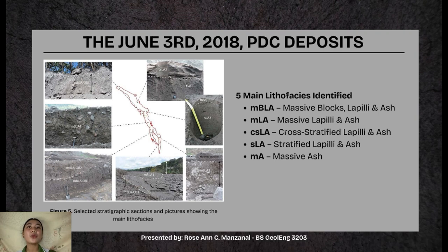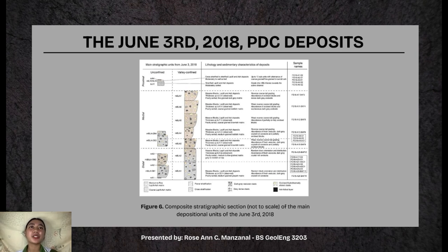In contrast, the overbank deposits form when flows spilled out of the main channels. Some created wedge-shaped layers near the valley walls, while others were redirected into smaller tributaries. These were typically less sorted but still carried large blocks. They also found ash cloud surge deposits, which were layered and sometimes showed small dune-shaped structures. These lighter, more distant deposits often left thin ash layers and scorched vegetation, helping trace the timing and extent of the surges. By analyzing these deposits and their structures, scientists were able to link specific flows to specific areas of destruction, like the overbank units that buried San Miguel de los Lotes.